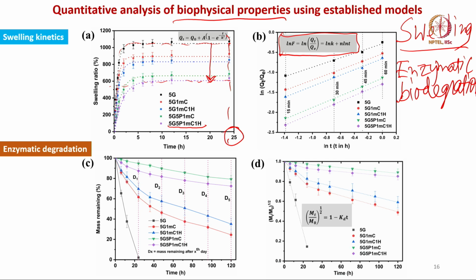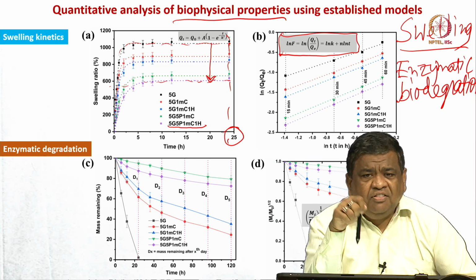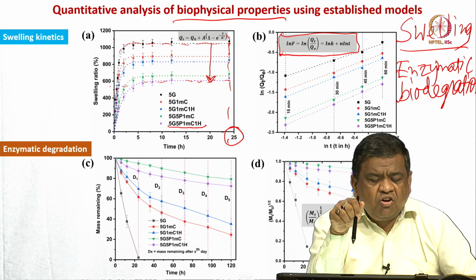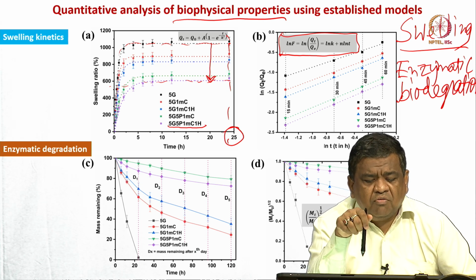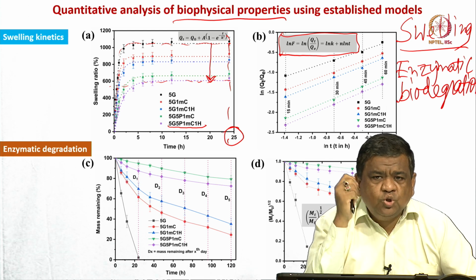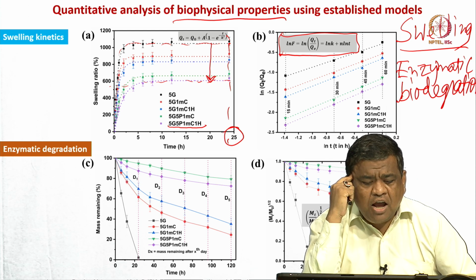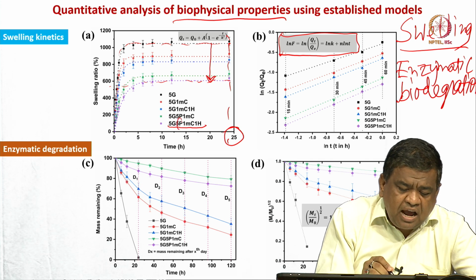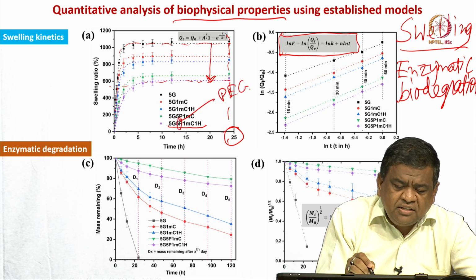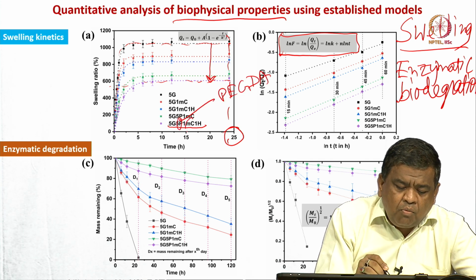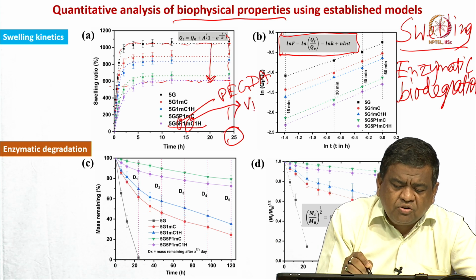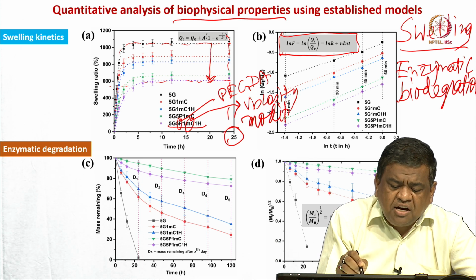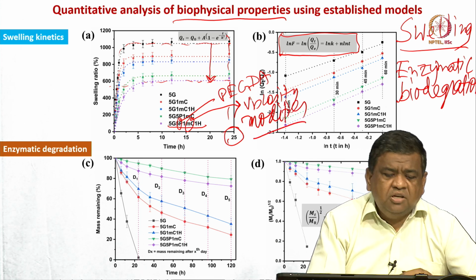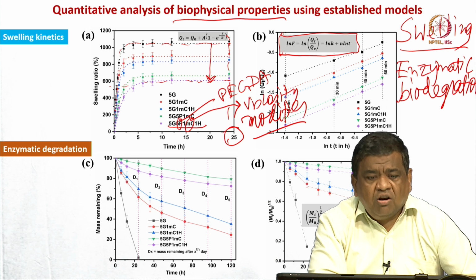So, the baseline hydrogel, that is 5% GelMA, when you add this inorganic component and then a secondary cross linker and also a viscosity modifier, then it is reduced to almost half. So, I repeat, P stands for PEGDA, that is the secondary cross linker. Modified carboxymethyl cellulose is the viscosity modifier, right, and hydroxyapatite addition is essentially to improve the stiffness or strength properties because these are inorganic constituents.